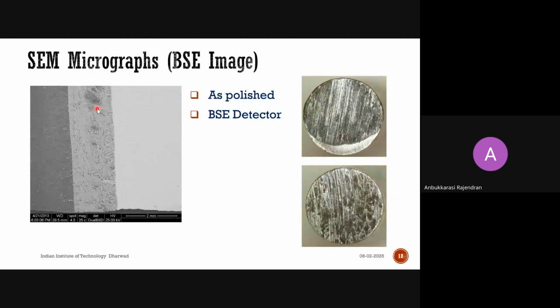Another one is again an intermediate layer. To reveal this intermetallic layer between aluminum and copper at one particular condition, I chose a BSE detector. As I mentioned, if you are expecting a contrast difference or any density difference features in your structure, you can go for BSE mode and try to capture those images. This is one of the wear tested samples, a pin on disk experiment. After the wear experiment, the morphology of the worn surface of the pin was captured by using SEM.